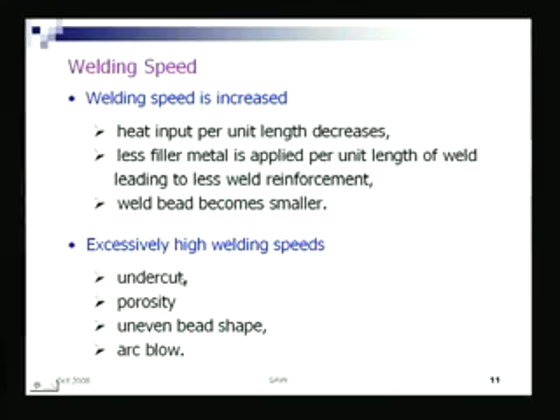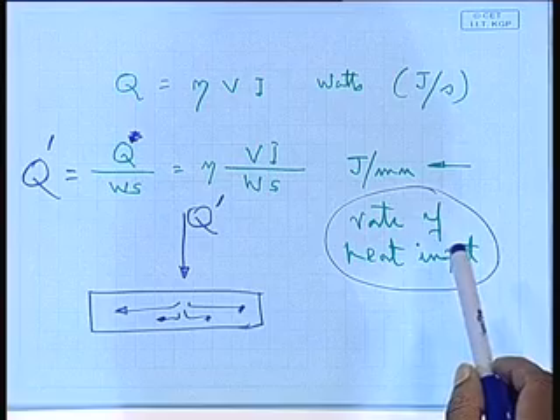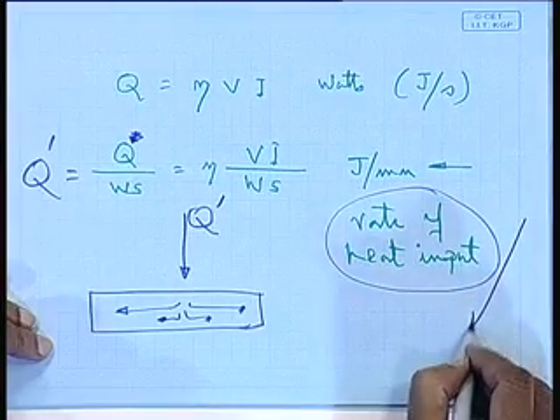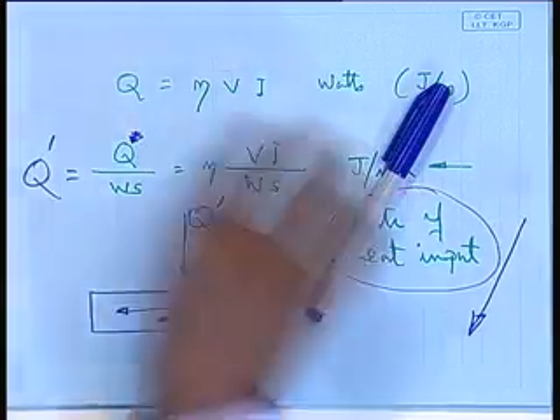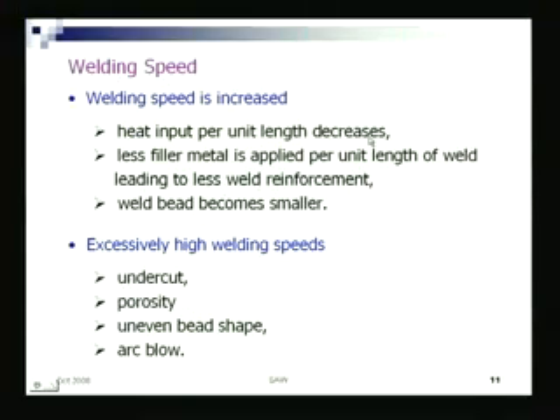The other aspect is that if I increase the speed, the rate of heat input decreases. So, if I want to reduce distortion, first and foremost is to see how I can implement a welding process which has a low rate of heat input. That rate of heat input has to be reduced, right. So, that is what we see here, that heat input per unit length decreases as you increase the welding speed. So, increasing welding speed not only benefits productivity, but also the quality of the final structure. Your residual stresses will be less, your distortions will be less.